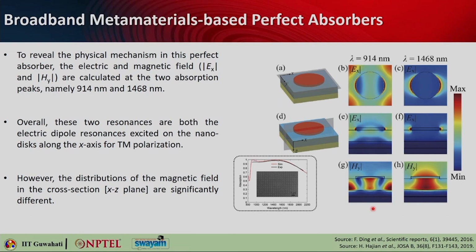Okay, and since titanium is very dispersive and has a relatively large imaginary part, if you look into the dispersion relation, you will get to know that the intrinsic absorption coefficient of titanium is very large. So you can understand that the quality factor of the resonance of this localized surface plasmon resonance peak here is rather low,